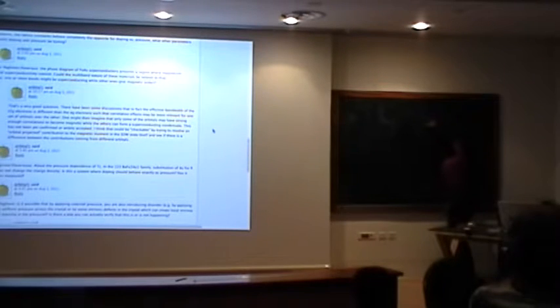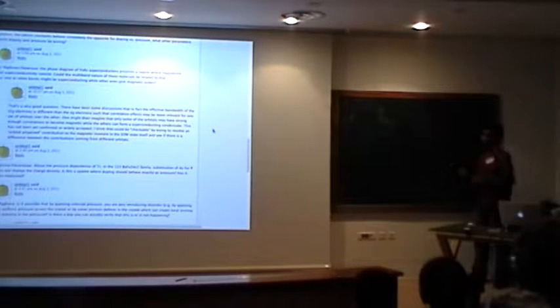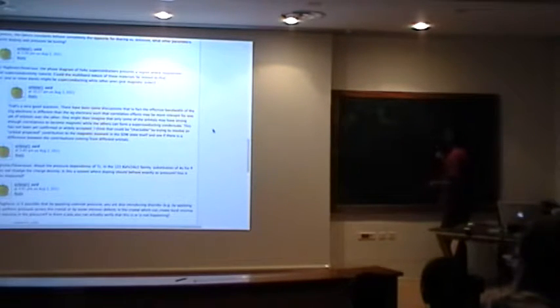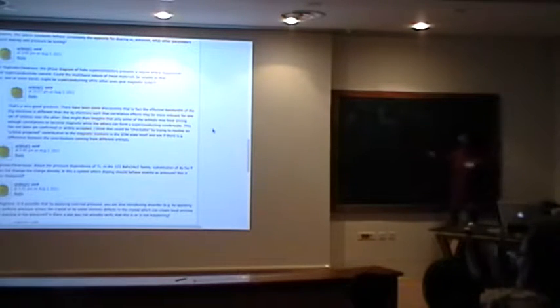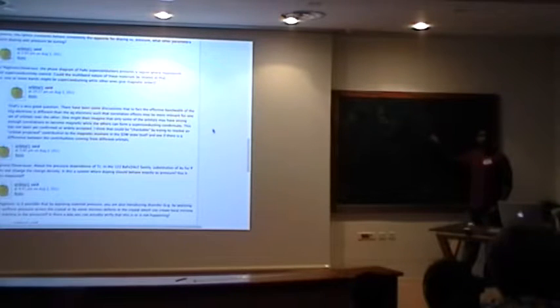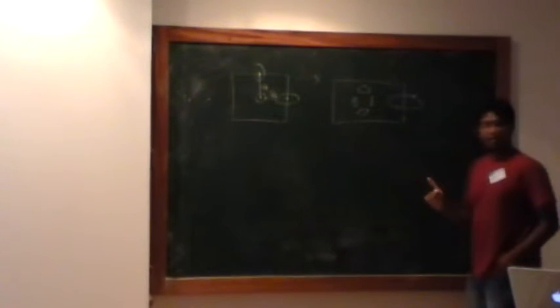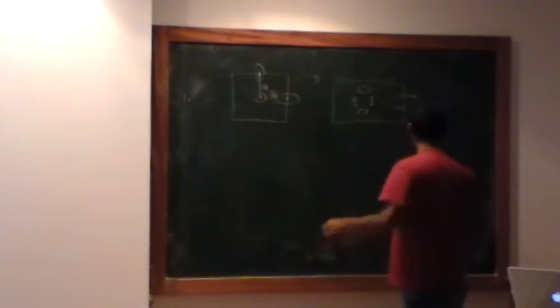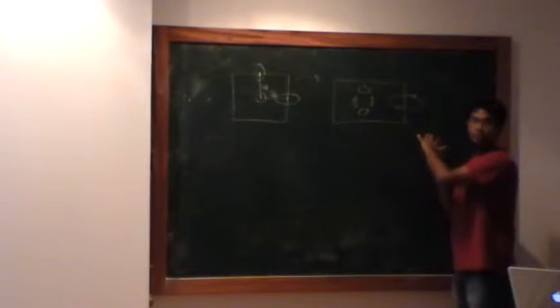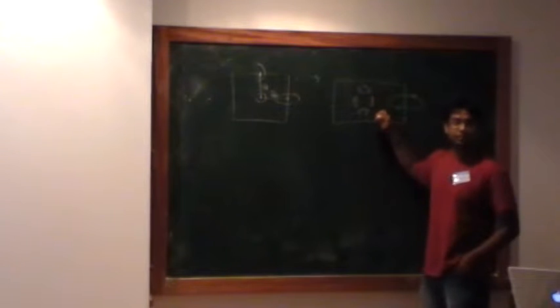What is interesting is there are still residual Fermi surfaces which are left. One can call them the reconstructed Fermi surface in this new Brillouin zone. Now, the question that is put forward is, well, if this has already taken part in the formation of the magnetic order, can this band give rise to superconductivity? Which naively one will say yes, which is fine. This by itself can lead to superconductivity with K, minus K kind of pairing. But there's a much more interesting thing, that is, this pocket can entirely be forgotten. In the sense, you can have superconductivity even in this reconstructed Brillouin zone.